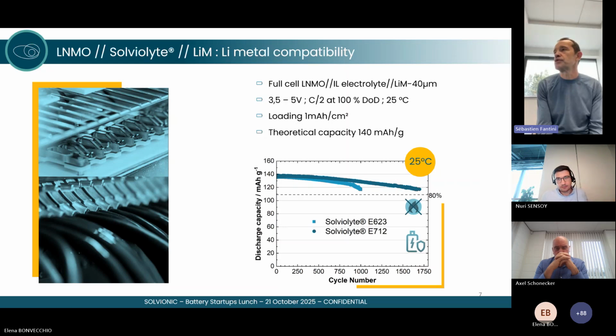Here we only show the C/2 cycling steps, but there is also a formation step that is not shown here, but the formation step is kind of regular compared to state-of-the-art electrolytes. So 100% depth of discharge and room temperature cycling. You can see here that the cycling stability of our electrolyte with 2 different Solviolyte formulations is quite good.